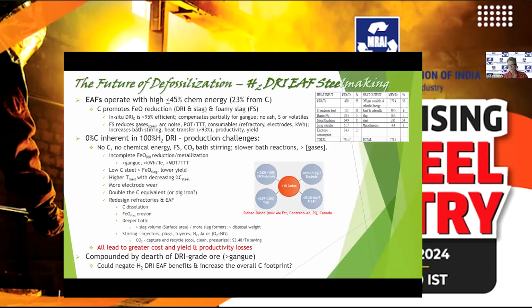Arc furnaces, as we all know, operate with a high chemical energy input, and the little chart here on the right shows that 23% of that comes from carbon. It promotes the FeO reduction in the slag and in the DRI, and it creates the foamy slag, and all the benefits are actually there. If we have zero carbon coming in from the 100% DRI, we're going to have some major challenges.